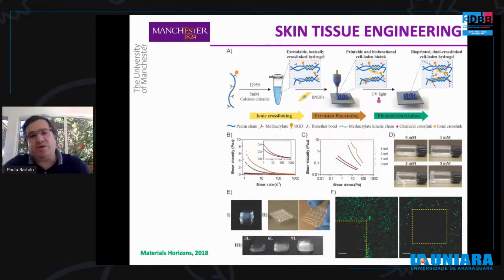So the pectin was decorated with RGDs, encapsulated human dermal fibroblasts. We add calcium chloride into the polymer solution to slightly increase the viscosity through an ionic cross-linking to guarantee a good printability of the bio-ink. And then the bio-ink is printed and finally cross-linked through a UV curing reaction.